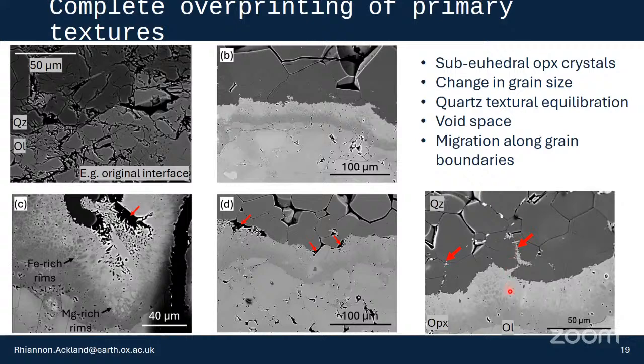And very interestingly, the OPX is not limited to the initial interface between the quartz and the olivine. In some places, we saw it migrating along the quartz grain boundaries, and even in some places developing subhedral OPX crystals. So there's a complete overprinting of any primary magmatic textures we might see with secondary replacive textures.